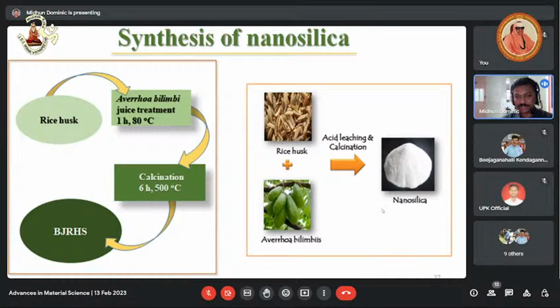We were surprised with the results because the Averrhoa bilimbi fruit is a rich source of oxalic acid. The oxalic acid content in the Averrhoa bilimbi is enough to eliminate all the other metallic impurities present in rice husk, like sodium, potassium, and calcium. But in the literature, several scientists have used concentrated hydrochloric acid, sulfuric acid, nitric acid, and even aqua regia and piranha solution for removing metallic impurities from rice husk.